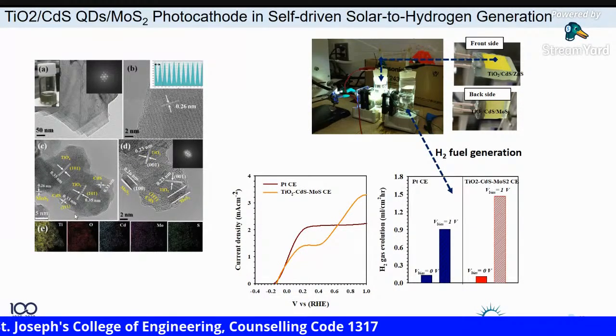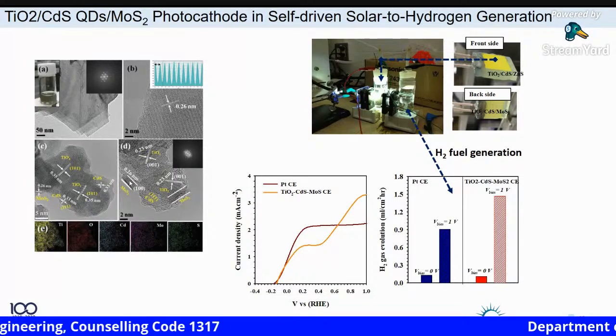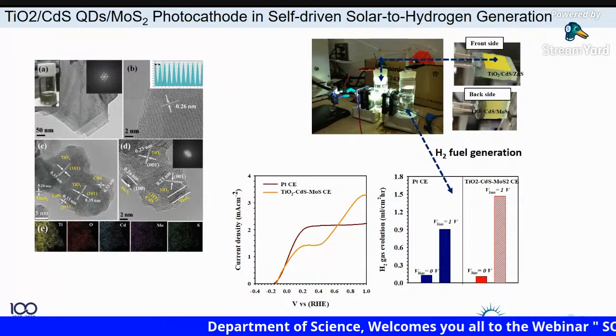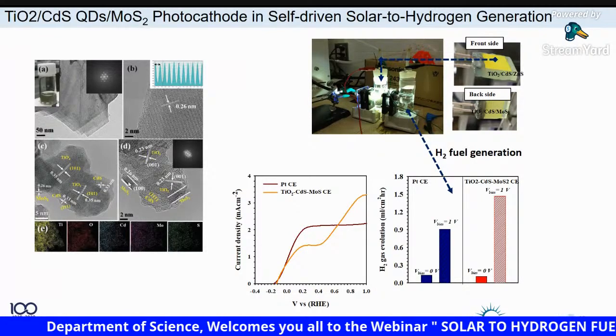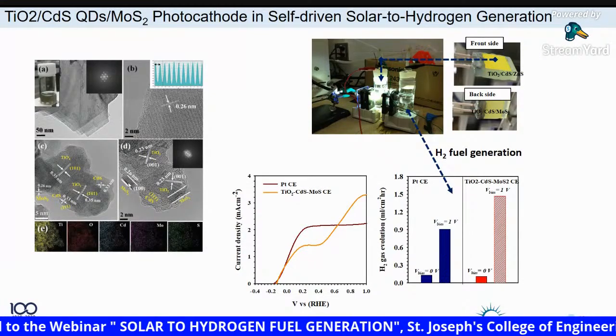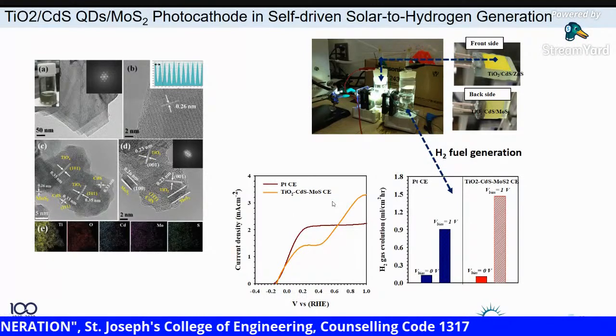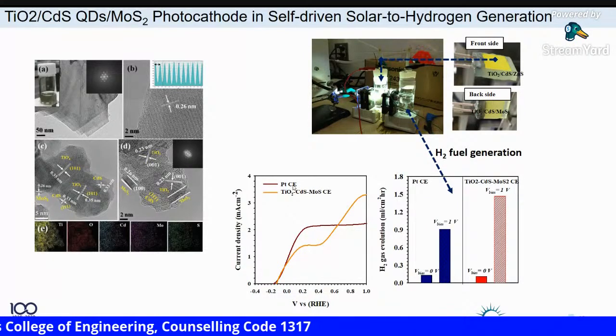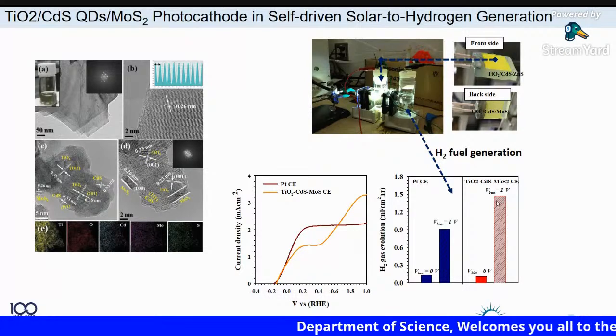And you can see some of the molybdenum sulfide here. It's a 1T structure, a sheet-like structure, MoS2. This is a dark catalyst. So this overall TiO2, cadmium sulfide, MoS2 structure acted as a photocathode. So we completely replaced our platinum wire, the platinum cathode. Still it's working very well and shows a feasible, comparable hydrogen evolution performance.